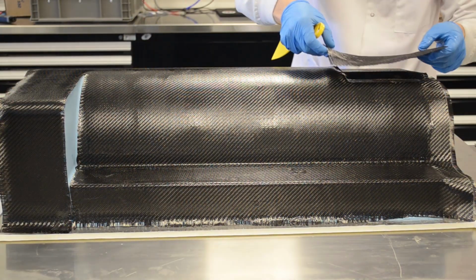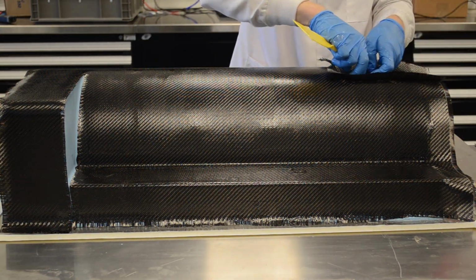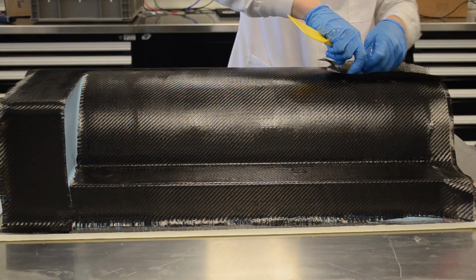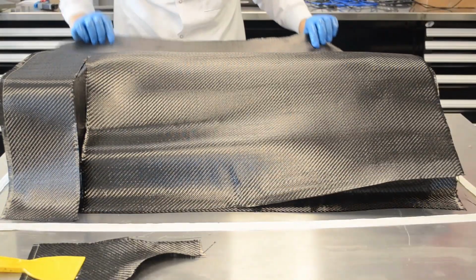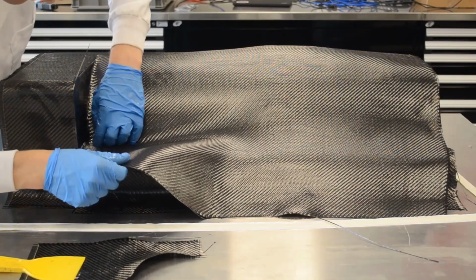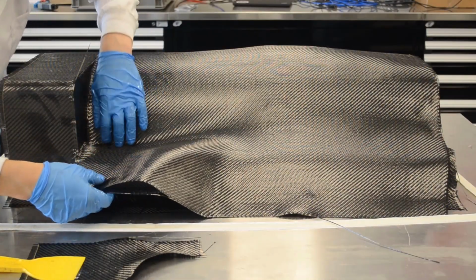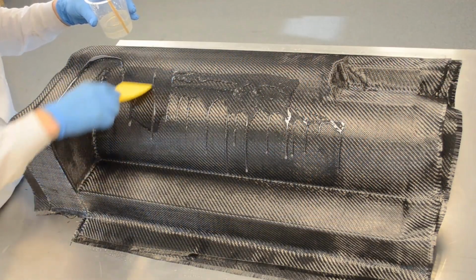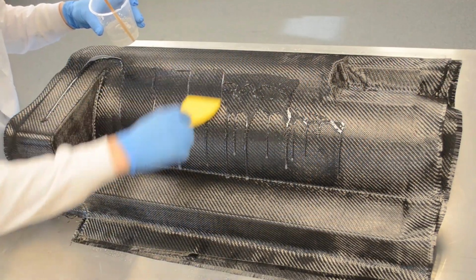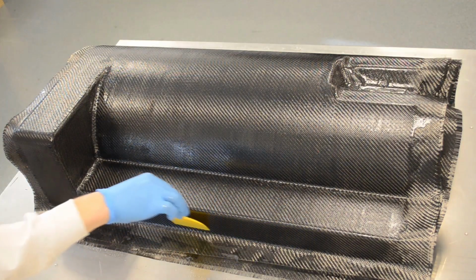For the first part, a vacuum bag will not be used. Resin with a 20 to 25 minute pot life is used, and the first layer has begun to gel while the second layer is being saturated. This can help hold the first layer in place while it is being positioned and wet out. It is important that enough working time is available to ensure that the part is evenly saturated and that there are no wet or dry spots.